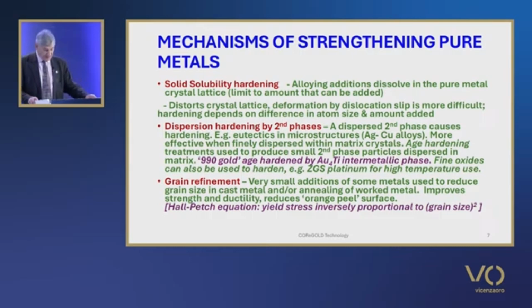Typically, in such alloys, the amount of alloying addition exceeds the limit of solid solubility, and second phases of different composition and/or crystal lattice are formed. By careful processing, these can be precipitated out into the parent metal crystal lattice as dispersions of very fine particles. This is known as age hardening or precipitation hardening and is commonly utilised in the carat golds and some platinum alloys. The 990 gold-titanium alloy, which I referred to earlier, is hardened by a gold-4-titanium intermetallic phase, for example.